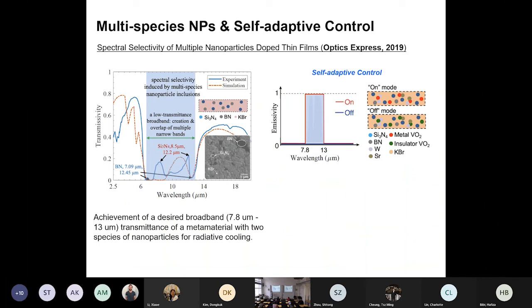Other than silicon nitride and boron nitride, we also added VO2, vanadium dioxide. VO2 is one type of phase transition material. It goes from solid phase to solid phase, from metallic to insulating phase. So with the inclusion of VO2 nanoparticles or VO2 thin films, it could turn this material on and off. It could turn on, meaning we can open up this window for cooling, and we can also turn it off, to make sure there is no cooling at all. It's going to keep it warm.